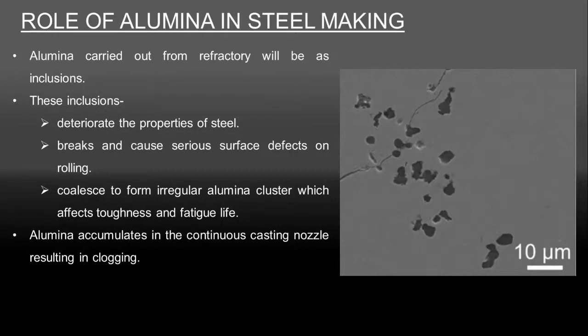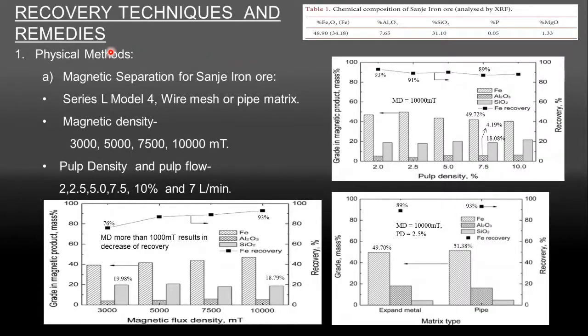They are brittle in nature, and as a result, while rolling, they break, causing serious surface defects. When they coalesce, they form irregular clusters, which degrades the toughness and fatigue life of steel. Even while casting of steel, alumina accumulates in the nozzle, which results in clogging of that nozzle. Coming to recovery techniques and remedies, one of the research-based recovery techniques is magnetic separation of Sanje iron ore and iron ore in Zambia.